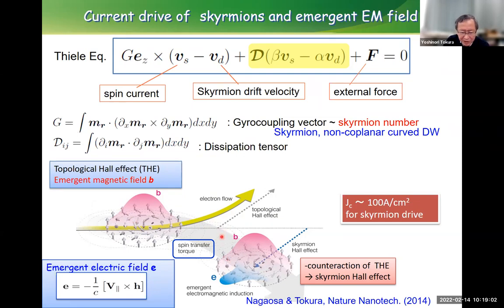And more importantly, the dynamics of the skyrmion particle itself cause a kind of electric field, because it carries a magnetic induction. So it can cause electromagnetic induction. It's proportional to the skyrmion B field and also the skyrmion velocity vector, around this region.